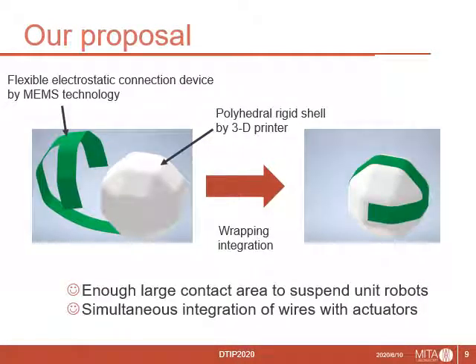From this consideration, we propose a flexible electrostatic connecting device and its wrapping integration method. Our proposed device consists of electrostatic actuators and wires which provide them with driving energy on a flexible substrate. The device is integrated to a unit robot by wrapping it to a 3D printed polyhedral rigid shell. This method realizes a large contact area and simultaneous integration of wires with actuators.